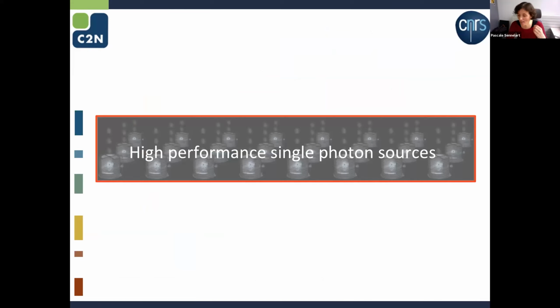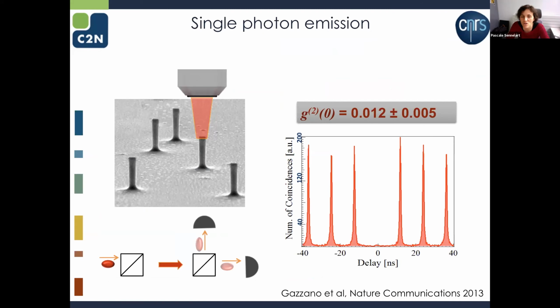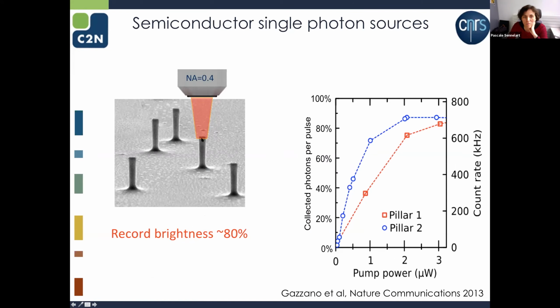So with this, we fabricated high performance single photon sources. This was a turning point for our technology. So with just the devices I've just shown you here, we tested the single photon purity here. So we excite and collect the single photons. And I told you that if there is just one photon, I will never have to click on the two outputs. And the absence of peak here at 0 delay is a signature of that. So this is a high single photon purity single photon source. And then we can measure the probability that I do have a photon here that comes into my first objective lens here. So in 2013, we could show that we can have a single photon source with a probability of having a photon of 80%, which is still the record efficiency for a single photon source, all systems considered. But you see here, it's like 100 times more than what you can get with parametric down conversion sources.